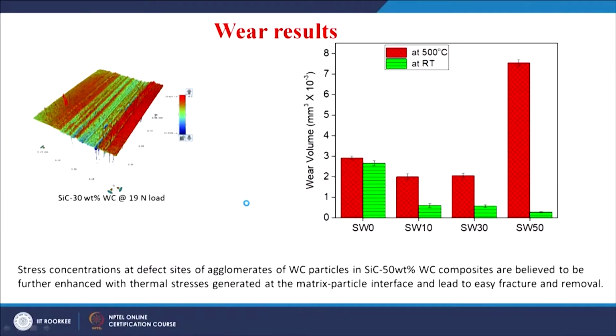When comparing the results obtained in reciprocatory sliding conditions at different temperatures, room temperature and 500 degree Celsius, you can see that silicon carbide tungsten carbide composites always show higher wear when worn at elevated temperatures compared to the room temperature. In silicon carbide ceramics, the difference is very much less. It is believed that stress concentrations at the defect sites are attributed for the increased wear. Also, at the higher temperatures the materials soften, so the strength is reduced, and you get more material removed from the surface.